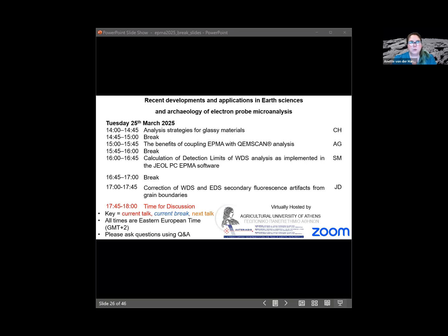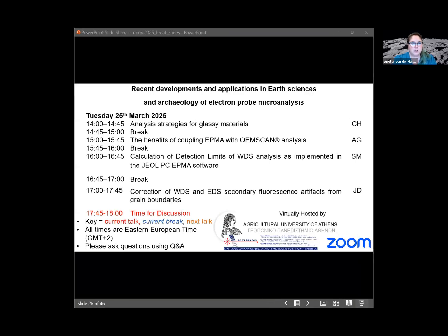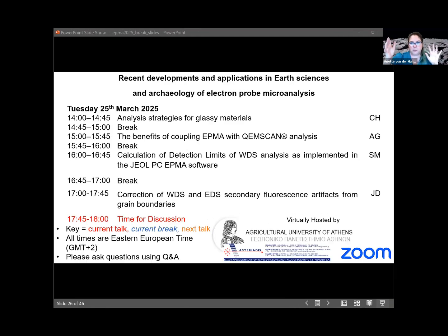An additional thing, which is a mix of comment or question, is a good tip that I once got. If you have geometric problems or questions, like where is my spectrometer relative to the sample, and you want to test that, or test whether your correction works, of course, the problem is we can't change the orientation of the spectrometer. Sometimes you're lucky, you have the same crystal in opposite directions, so you can see how the data corresponds. But what we can do is put the sample in the other way around.